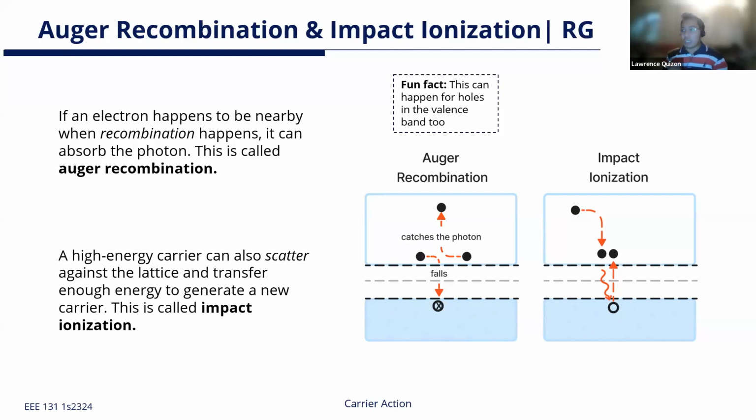That's Auger recombination. Next is also about collision, no? Impact ionization is what you call it. This next happening is when an electron very high in the conduction band meets an electron that's low in the valence band. If those two collide, the electron that's high in the conduction band goes down to just barely in the conduction band, but it gives a lot of energy to the electron that's in the valence band, enough to promote it, no?